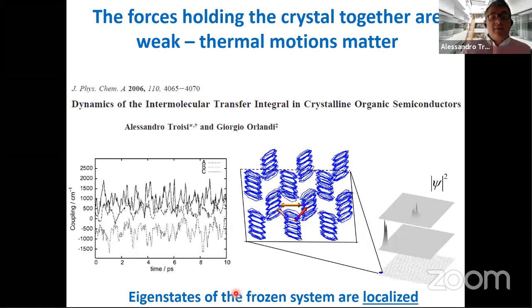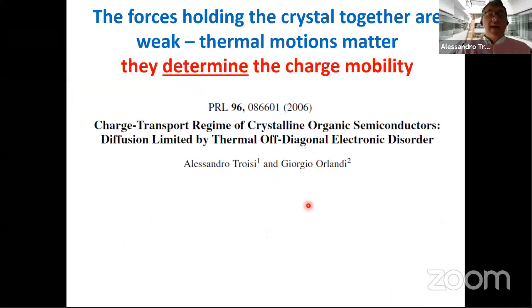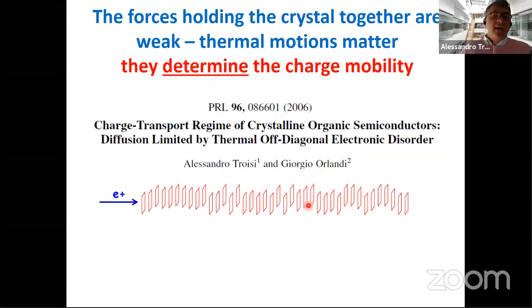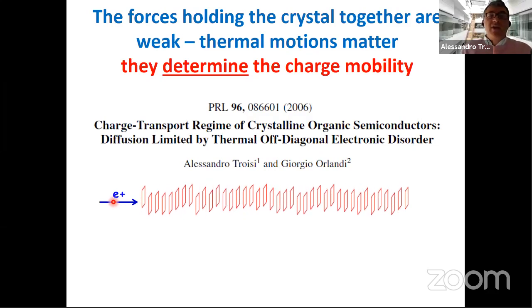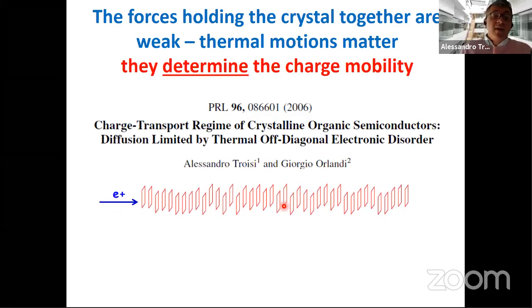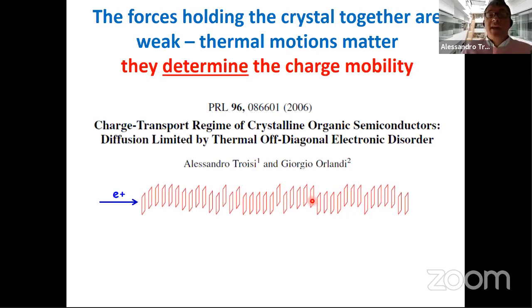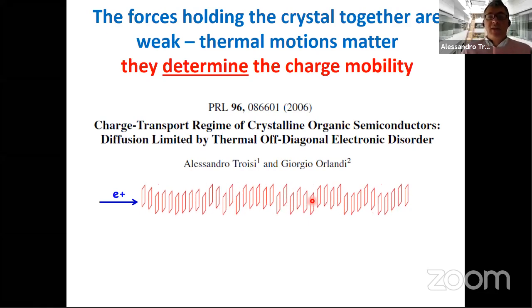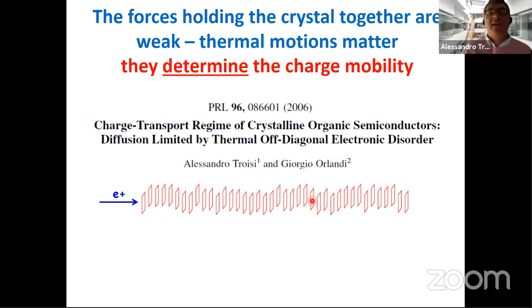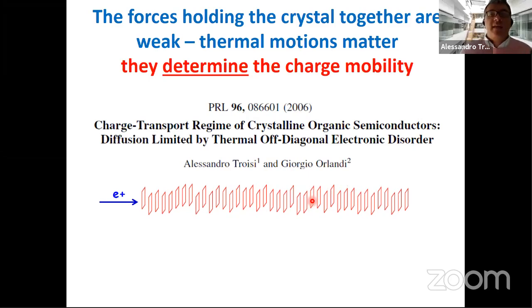So the situation explains why the scattering is so frequent. Essentially, the non-local electron-phonon coupling is very large. So the coupling of the electrons or the holes with the motion of a molecule. A cartoon that explains the mobility was proposed more or less at the same time. And you can imagine that the electron or the charge is moving and the lattice is oscillating with large amplitude, more or less with the same time scale as the electron passing through it. So it's not possible to do the time scale separation. That's why band theory fails. That's why the mobility is so small.